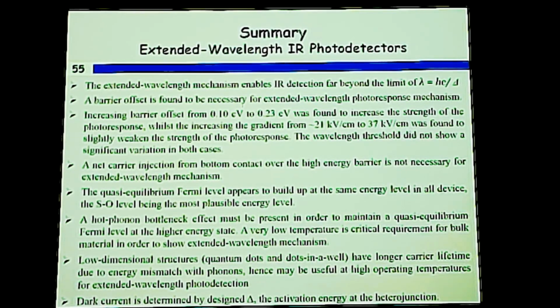And also from the temperature dependence of the mechanism, we found that the hot phonon bottleneck effect is a critical requirement for this mechanism. Based on this finding, if we use low dimensional structures, meaning quantum dots and quantum dots in a well, where there is energy confinement to have energy mismatch with the phonons, we can expect that the operating temperature of these devices with the extended wavelength mechanism can be higher. We can get high operating temperature. And the dark current appears to be determined by the designed value of the heterostructure, not the delta corresponding to the extended photoresponse.